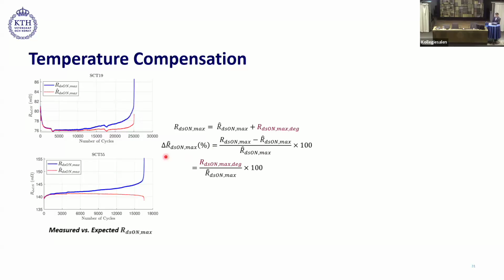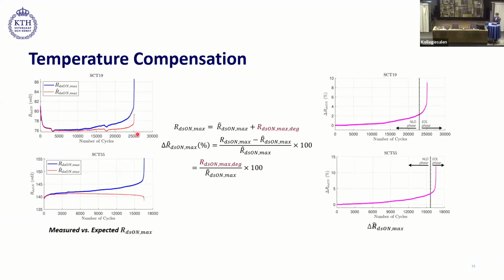Here, delta RDS on max represents the temperature compensated parameter. So after feeding these signals into this compensation method, we get this output delta RDS on max. That is the temperature compensated on-state resistance. There are a few important things to note here. The first one is that the signal showed a linear drift initially, like here and also here. However, towards the end, the drift becomes exponential, like here and here.